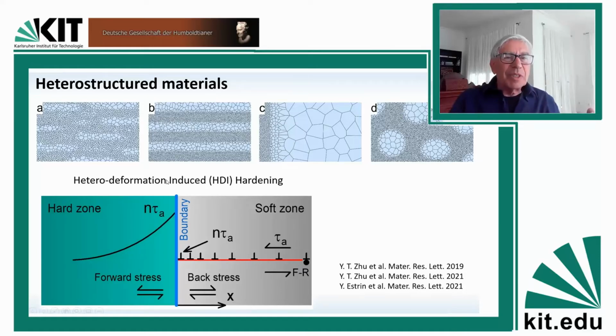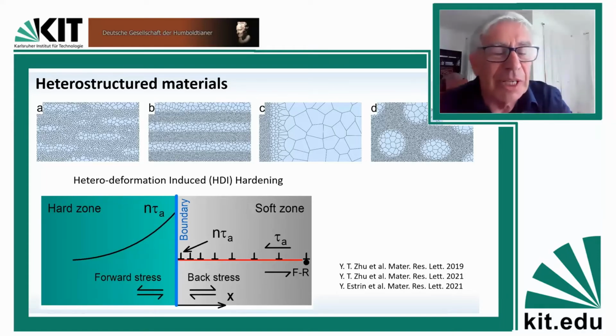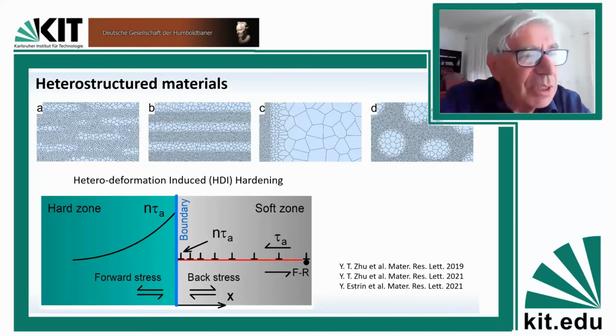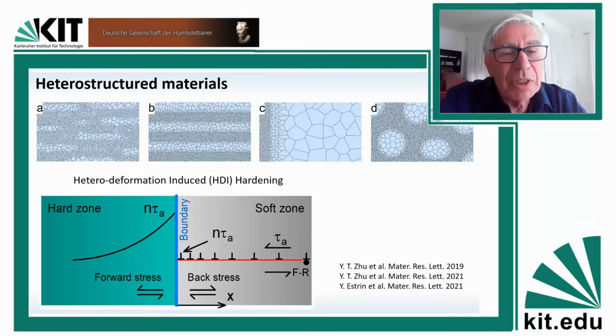The boundaries between such layers play an immense role because that's where dislocations get piled up. They cannot penetrate across the boundary. They can raise the stress in the adjacent zone to that level so that they produce a forward stress in the hard zone, but such a dislocation pile up also produces a back stress in the softer zone. And that gives you the so-called kinematic hardening, which enhances the mechanical strength of the material.